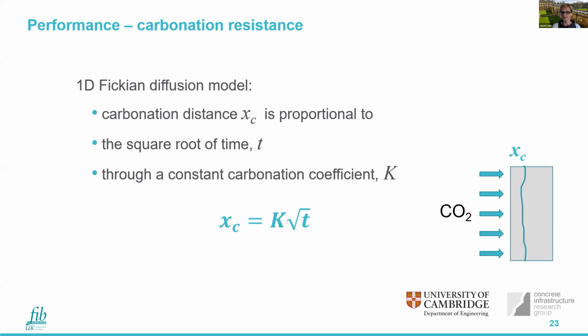If we now put in, say, for example, a durability requirement, in this case, carbonation resistance. Carbonation is typically modeled using a 1D Fickian diffusion model, where we look at carbonation distance, which is XC, proportional to the square root of time T, through a constant carbonation coefficient K. And there's a little icon on the right of this slide to show you what that means. So I think for the purposes of what I want to describe next, the key thing to think about is, say, if we have a particular design life, that fixes T. If we then have a carbonation front requirement, then we can work back to find out what K would be.